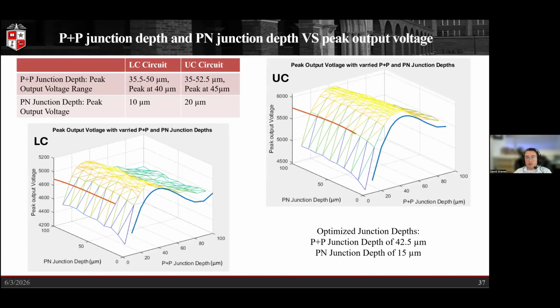And so doing these optimization sweeps, we found some curves here. With that, we found that for the lower corner circuit and the upper corner circuit, we found peaks at 40 and 45 microns respectively for our P plus P junction depth. For our PN junction depth, we ended up finding peak output voltages at 10 microns and 20 microns. And so we decided to split the difference and optimize between both circuits, with a P plus P junction depth of 42.5 microns and a PN junction depth extending that to 15 microns.